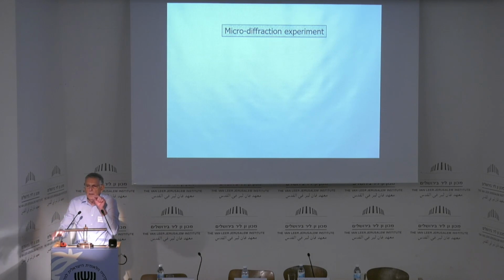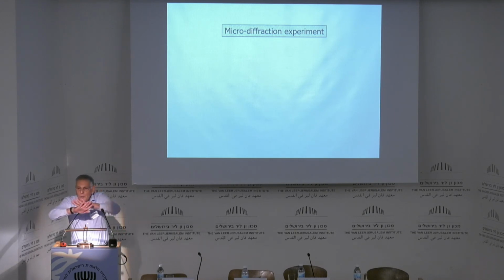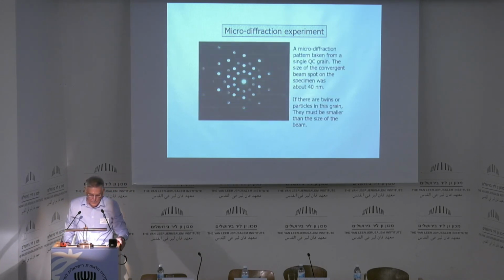And hit a point. If that point contains just one twin, then I'll have a periodic diffraction pattern. If it contains two twins, I'll get 1, 2. But anywhere I went, I received the same 5-fold rotational symmetry diffraction pattern. No twins. I knew from day one, from that afternoon, that there are no twins. I did not know what it was, but I knew what it was not, and it was not twins. Why do I mention it? Because later on, years later, the opposition claimed that these are twins. And I knew from that afternoon, no twins.